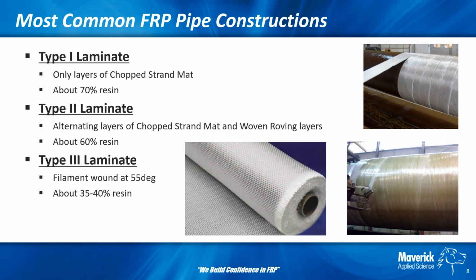And then type 3 is kind of a new designation in our new standards, but it's basically 55-degree filament wound pipe, a very optimal wind angle. This is the strongest, it's the most controlled, at about, I would say, 60 to 65% glass.